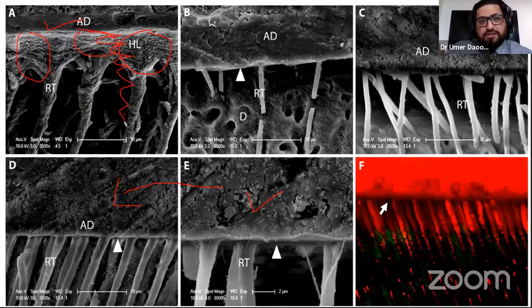So we use the etchant, we put the bonding agent, then the composite and all, and then we create the hybrid layer. But not over here. We did not create a hybrid layer, but we still had a good bond. What did we do? We used an ultrasound energy to remove the hydroxyapatite from the dentine structure, expose the collagen fibers, and then apply the bonding agent. So the bonding agent directly went on and attached itself to the intertubular and the peritubular dentinal structure and the collagen without creating the hybrid layer.